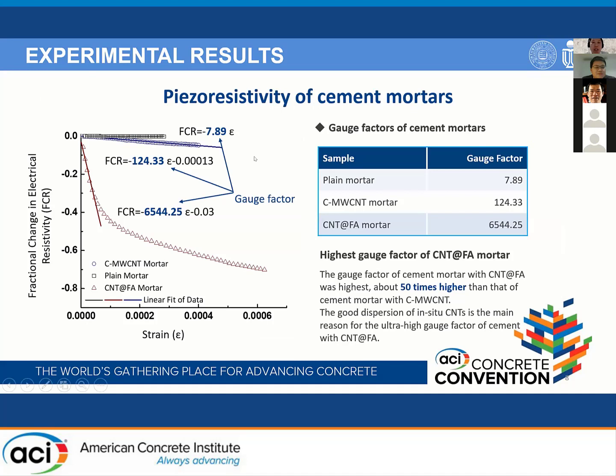Then we detected the piezoresistivity of the cement mortars. The fractional change in electrical resistivity of plain mortar, commercial carbon nanotubes cement mortar, as well as the CNT and FA mortar with increasing strain is shown in this figure. We can see that for commercial carbon nanotubes cement mortar and plain mortar, the resistivities decreased slightly and linearly with increasing strain. However, for CNT and FA cement mortar, the resistivity decreased significantly with increasing strain. Therefore, CNT and FA cement mortar seems to exhibit a more sensitive piezoresistivity compared with commercial carbon nanotube cement mortar.